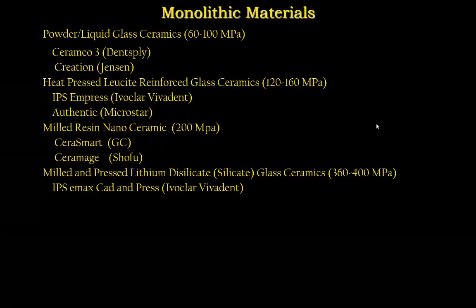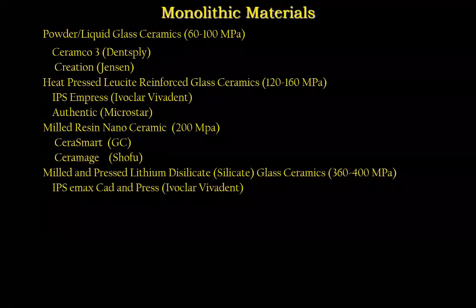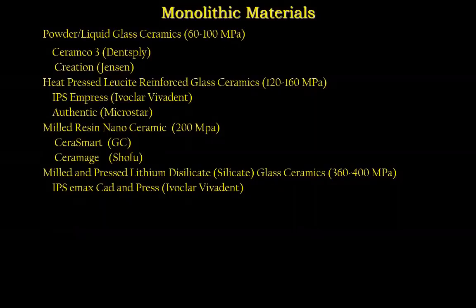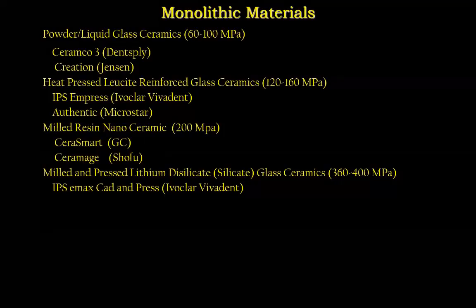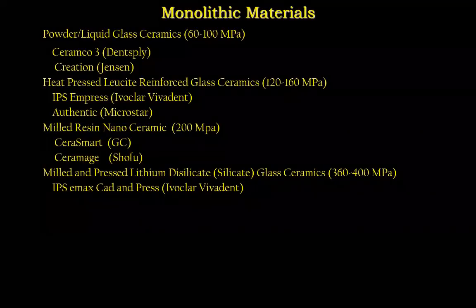So what we saw was a much stronger material that could be used for posterior crowns with a great deal of success. The other thing that was great about this material is that it was very aesthetic too. It had very good translucency and optical properties that allowed it to not only be strong, but to be very aesthetic. And then it could be cut back and layered, just like Empress was cut back and layered to even increase aesthetics. Ivoclar had a patent on this product.